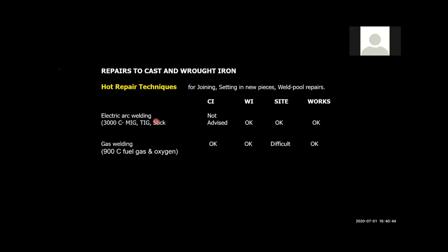So if we're worried about heating something to such a very high temperature and so quickly, why not instead use gas? Propane or acetylene used with oxygen. It will heat to about 900 degrees centigrade, but much more slowly. So that is okay for cast iron. You can heat up slowly, and it's okay for wrought iron, but of course on site, we really, again, don't want to have these hot works, and this is a very hot naked flame. So that's not a great idea on a site.